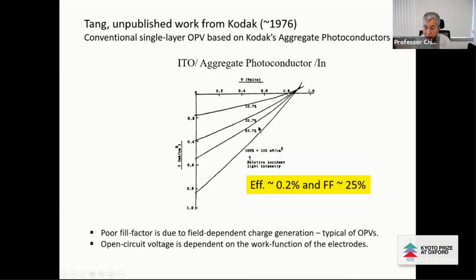For those who are familiar with solar cells, they immediately recognize that this is a very poor performance solar cell. The efficiency is roughly about 0.2%, and the fill factor is 25%. This is classic of early organic solar cells, a straight-line IV characteristic. The poor fill factor, I learned, is due to field-dependent charge generation.